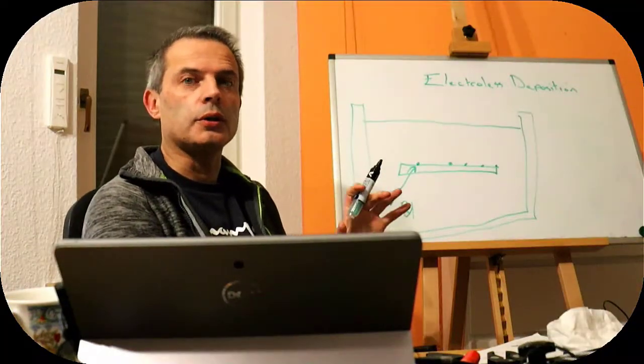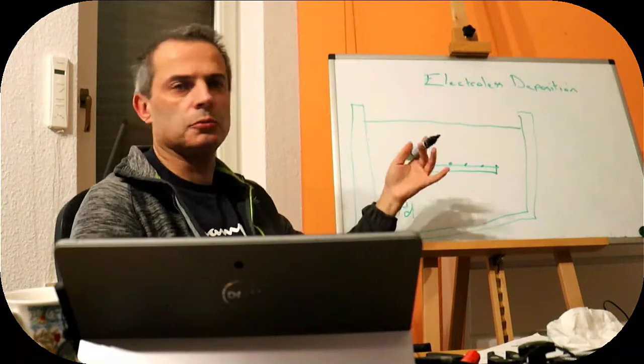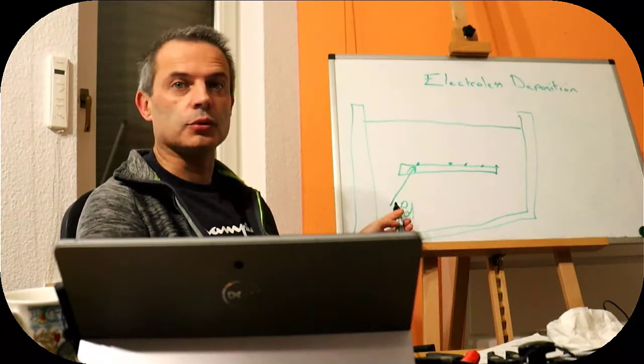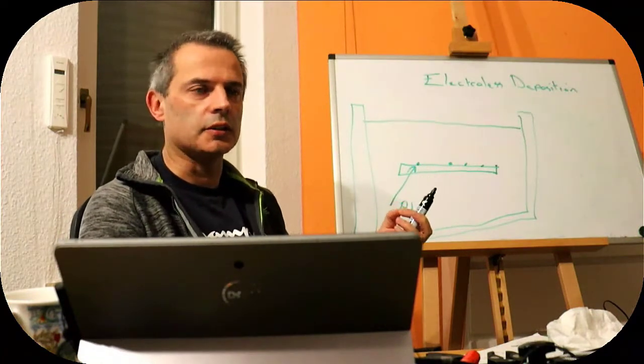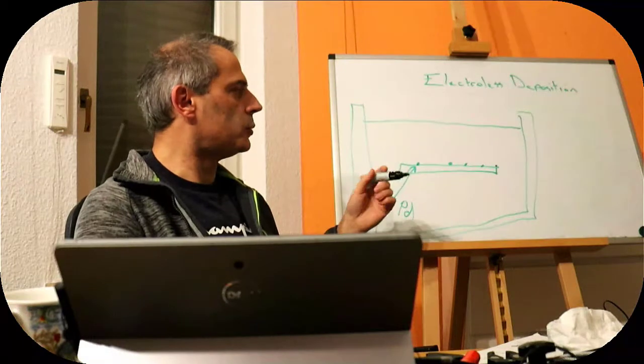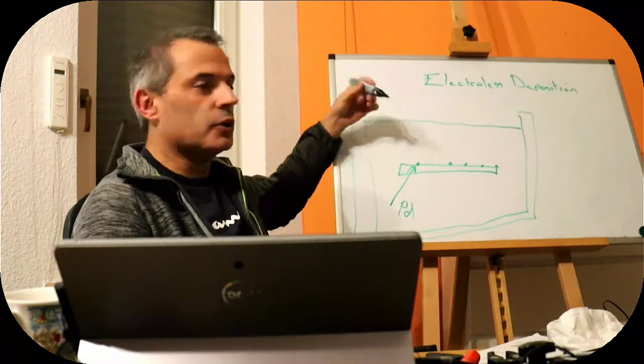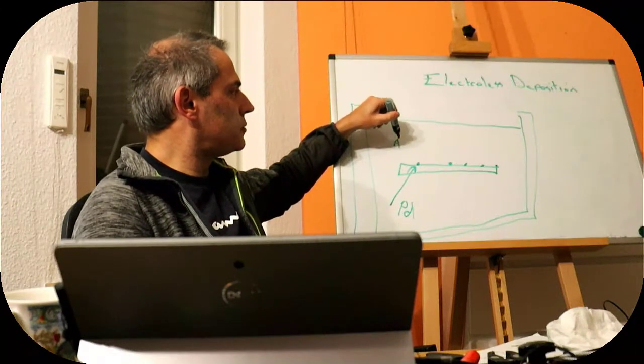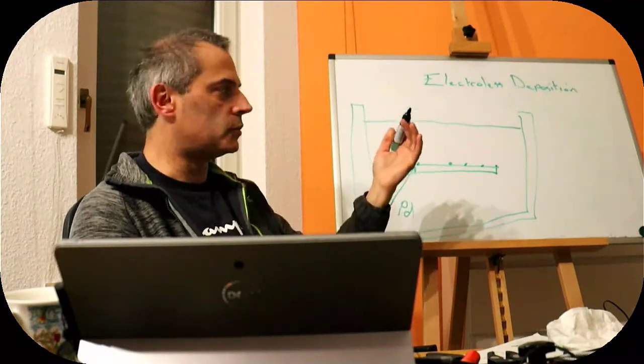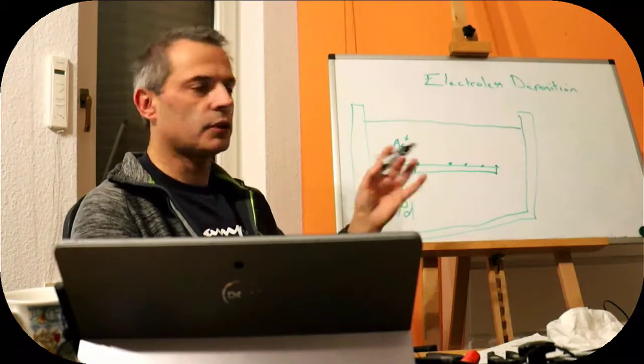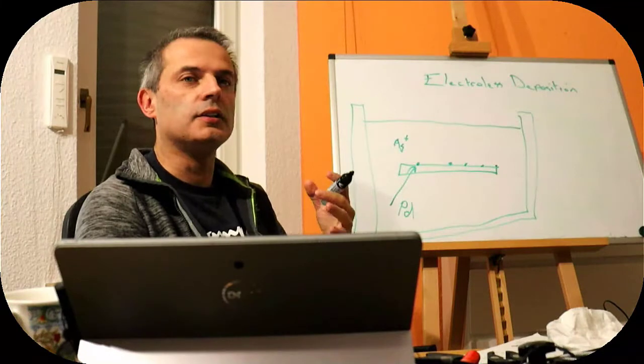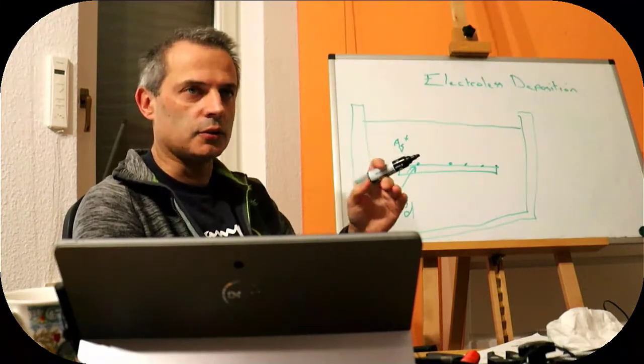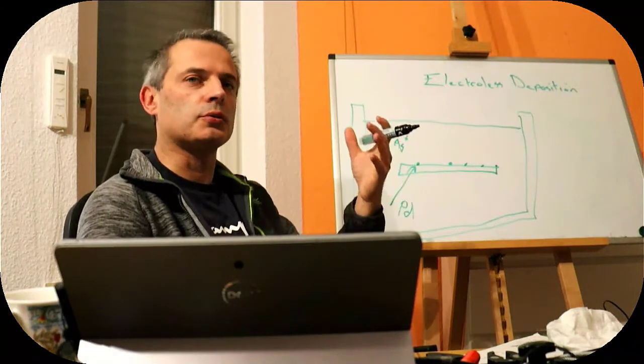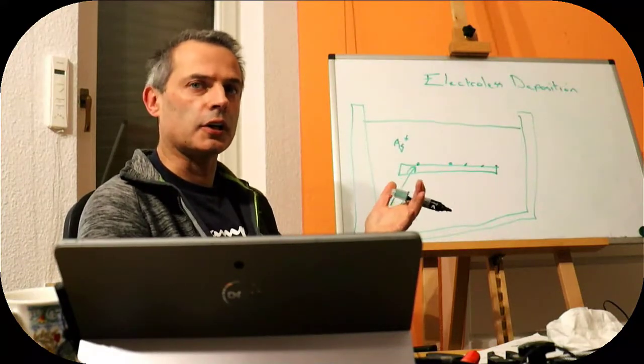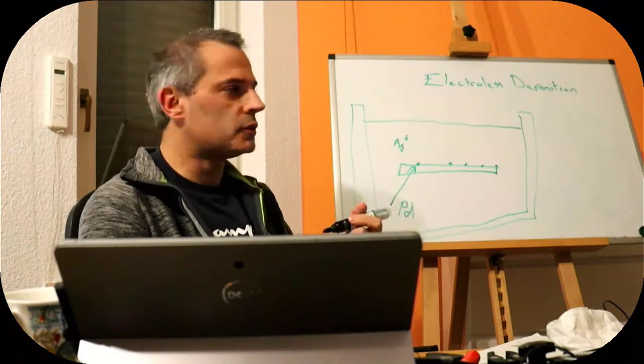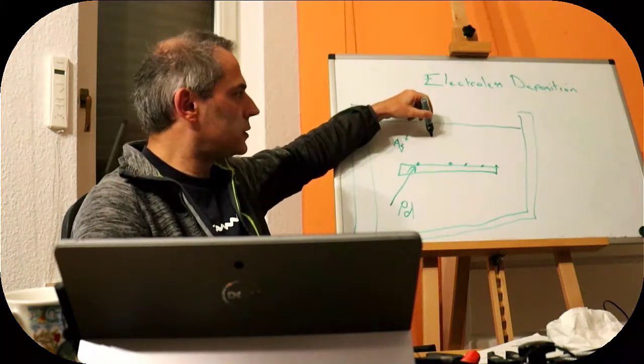So if we imagine a process where we're trying to electrolessly deposit silver onto some glass or something, we would have, first of all, some palladium particles. That's the typical catalyst for this. They have to be stuck to our glass, our non-conducting surface, and our silver ions are in solution, and also the reducing agent, which we will call citrate in this case, but it's not necessarily citrate. It needs to be a reducing agent that is just reducing, but is also complicated enough that it's difficult for it to occur in solution. Because it's difficult to occur in solution, we can't make new silver particles in solution.